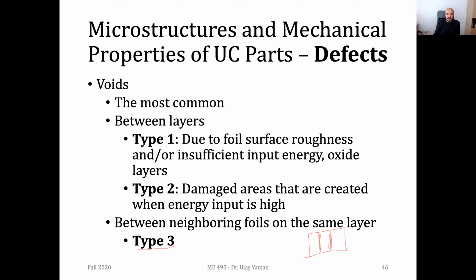Then we have type 1 and type 2 defects. These are between the layers. So if this is a side view, these are some layers, some foils. And again, depending on wrong parameters you are using, you may have some roughnesses on the layers, and this will result in some gaps, or you may have some specific damaged areas. If it's a damaged area, then it's called type 2, and these damaged regions are just due to the high energy input. You may have other problems like surface roughness or insufficient input energy, or you may have some oxidation between the layers. These are all called type 1 defects.